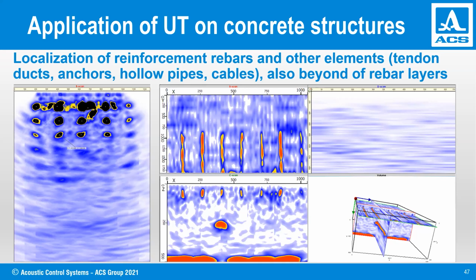But the color does not tell you much about whether it is a rebar or a void. We have to analyze it, and you can only analyze it well in 3D, because, for example, a rebar has a very clear shape. It is just a straight line inside the volume. If it is a void like honeycomb, it has a totally different shape. So we are talking about the shape of the indication, not about the color.